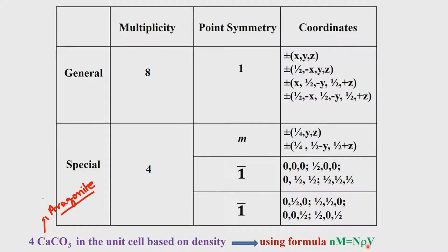So, what we do is we roughly take two liquids, one with a lower density and another with a higher density. These two solvents could have a property that this compound, calcium carbonate, will not dissolve in them. So, for example, in this case we cannot take water, it will dissolve in water. So, we have to take two solvents. Let us say we take alcohol on one hand and then some higher density liquid, which could be methylene bromide or methylene iodide or something like that. These solvents are chosen in such a way that calcium carbonate will not dissolve in them.